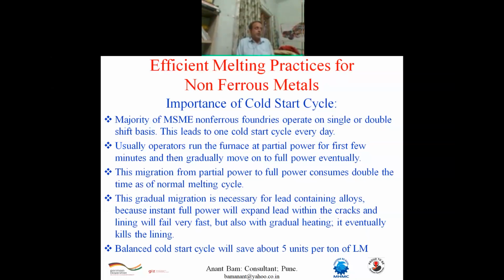We have to compromise on full power starting for leaded materials, as well as we need not waste too much energy by a very slow or very gradual start. Naturally, it is a practice that people consume double the time of the normal melting cycle for the cold start. But it can be squeezed to as close to 1.25 or 1.4 times of the normal melting cycle. Such an optimized cold start cycle can save up to 5 units per ton of liquid metal.